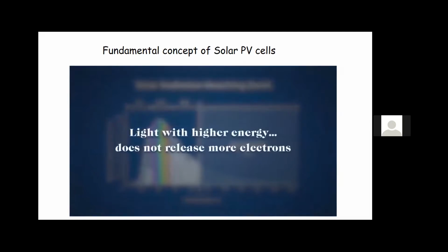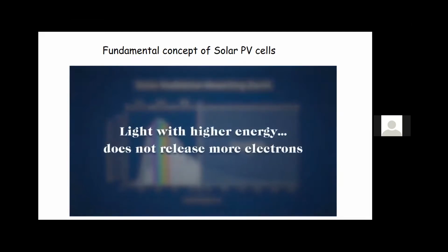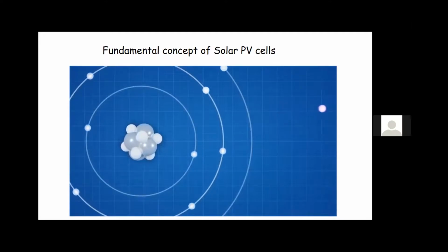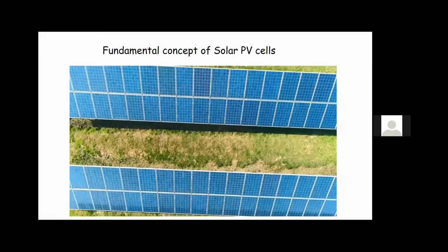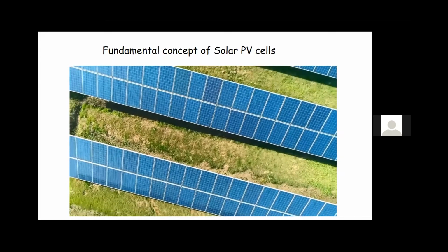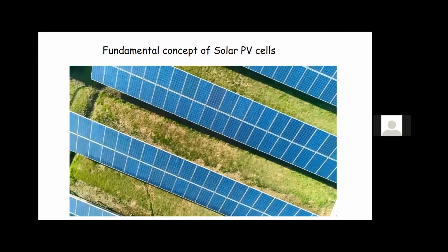Another thing to note is that light with higher energy does not release more electrons. It simply produces higher energy electrons. Blue light has roughly twice the energy of red light, but the electrons that blue light releases simply lose their extra energy in the form of heat, producing no extra electricity. This energy loss results in about 33% of sunlight's energy being lost. So, these spectrum losses alone cause a 52% loss in efficiency.